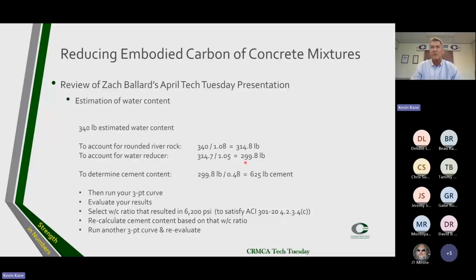Well, that number should look familiar to a lot of us. That's pretty much where our non-air entrained straight cement mixes are. Now, what do you do with this number now? Well, now you have to recalculate your cement content. So you take this 299.8, divide it by the water cement ratio that you needed for your 5,000 PSI, which was the 0.48. And that came from the table values from the ACI 211 document.